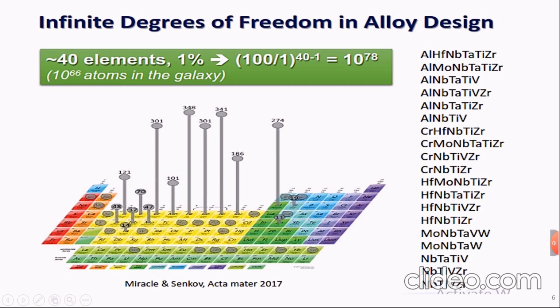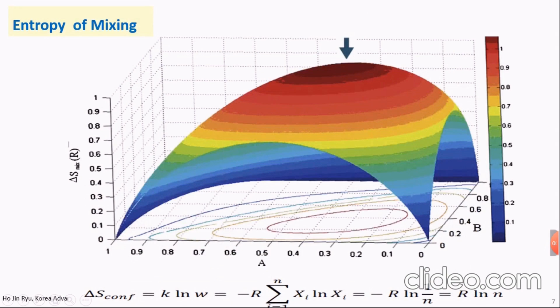So some people say that, okay, based on that concept, we can call it multi-component alloys or multi-principal alloys. Some others said, no, we'll call it high entropy alloys or equiatomic alloys. Why? Because the concept of high entropy alloys is you mix the elements in an equiatomic or near equiatomic manner to increase the entropy of the system. Why do you need to increase the entropy of the system? Because if you remember the Gibbs free energy equation, if you increase the entropy of the system, you will decrease the free energy. And if you decrease the free energy of the system, you can have solid solutions. That's why some people also call them solid solution alloys. Because in high entropy alloys, our main target is to have solid solutions, not intermetallics. You can have some intermetallics, but very limited. But the main concept is to design solid solutions.